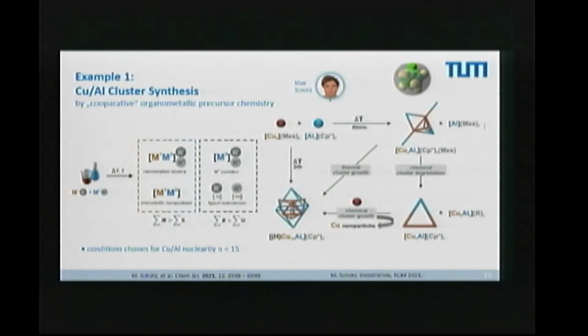And what is not shown is the hydrocarbon coating. I just left it away. It is not important at the moment. But you have to remind yourself, this is wrapped into this hydrocarbon shell. But this is not the only thing what is on this display. We have this copper 7,8, aluminum 6, and we have the copper 4, aluminum 4, etc., etc. Message is, by combining certain specific organometallic precursor compounds, by knowing about their cooperative chemistry, you can create clusters with a distribution of sizes. And this is shown here.